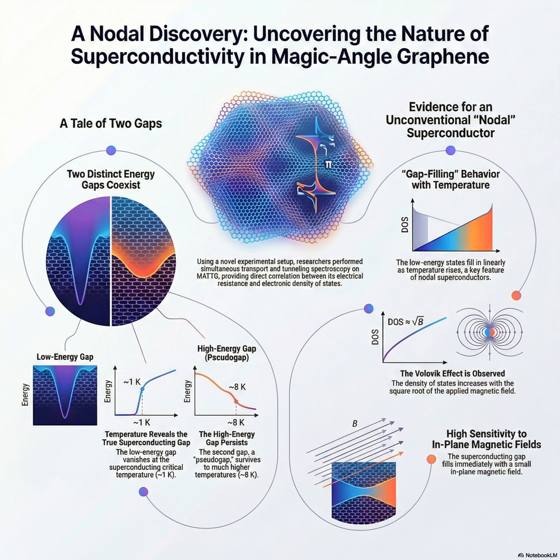Wow. So that's already linking this graphene system directly to the physics of high-temperature superconductors. It is. But the second piece of evidence, the one you called the wow fact earlier, this is the definitive proof. The Volovik effect. This sounds cool. It's truly beautiful physics. The team applied a small perpendicular magnetic field and tracked the increase in that zero bias conductance again. They were looking for a very specific, mathematically precise relationship. A relationship that was predicted decades ago, right?